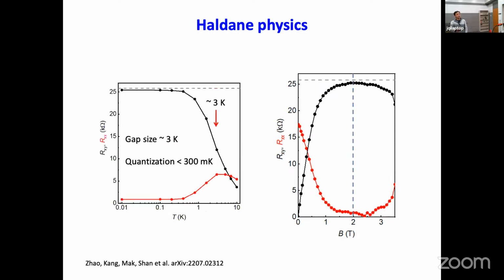You can also park at a particular magnetic field and do a temperature dependence. You basically see that the resistivity indeed drops to nearly 0 at low temperature, and the Hall resistance goes up to nearly the quantized level. And the energy gap for this particular system, the Haldane-Chern insulator, is about 3 Kelvin in this case from the temperature dependence. Okay. All right.